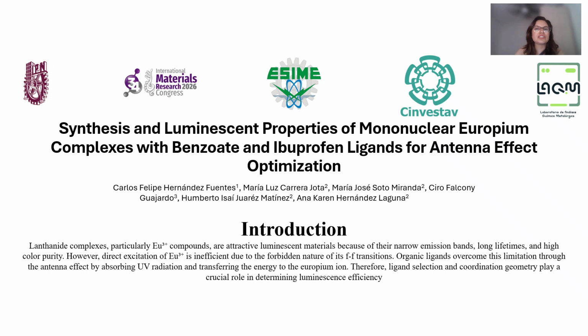Europium is one of the most attractive lanthanide ions because it exhibits intense red emission, narrow emission bands, excellent color purity, and long luminescence lifetimes. However, Europium absorbs light very inefficiently because its f-f electronic transitions are partly forbidden. To overcome this limitation, organic ligands are coordinated to the metal center. These ligands absorb ultraviolet radiation and transfer the absorbed energy to the europium ion through the antenna effect, significantly increasing